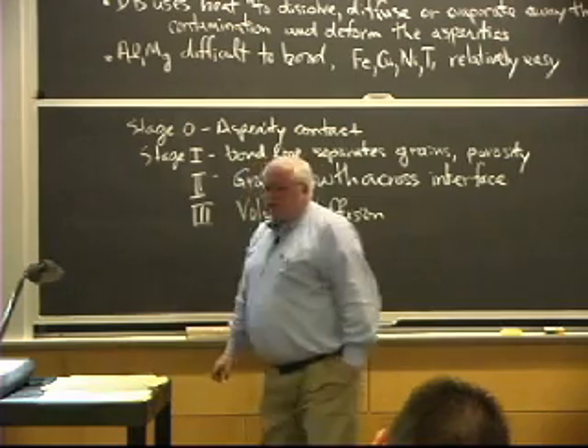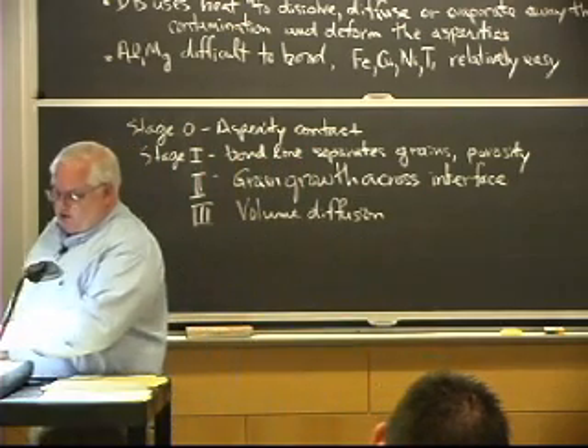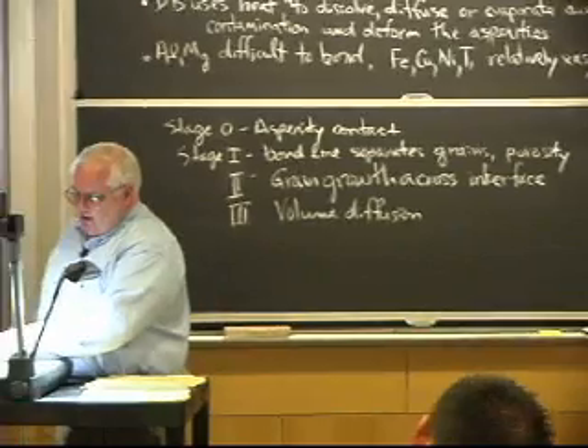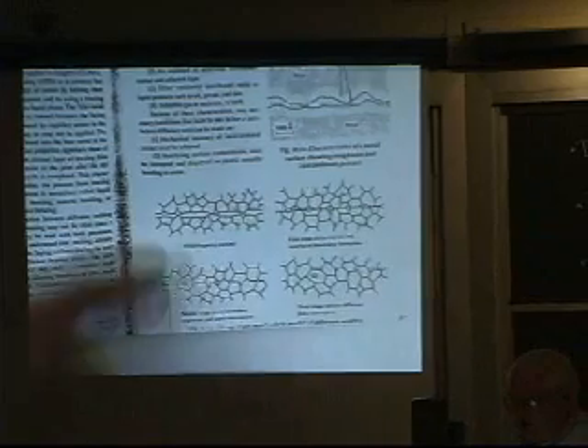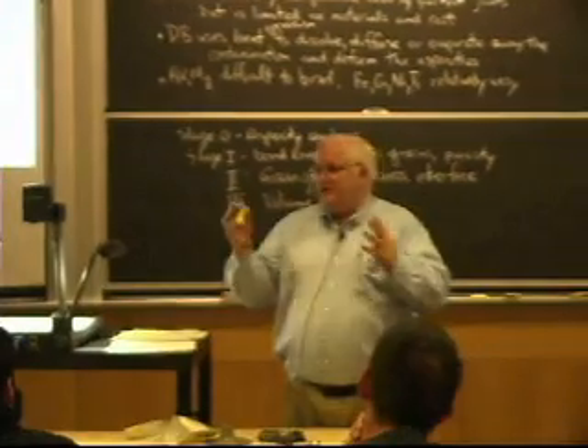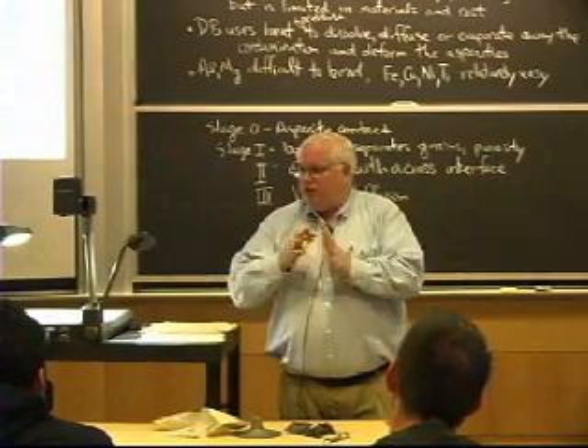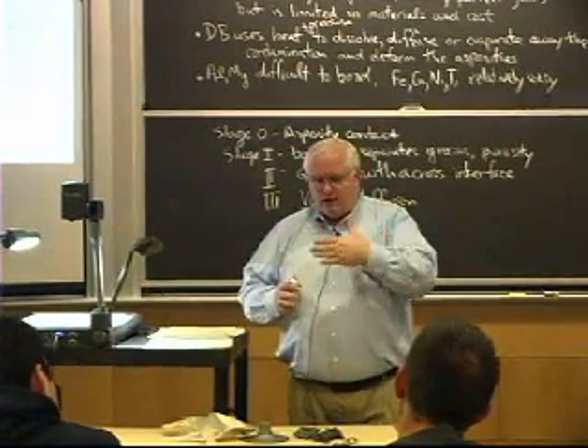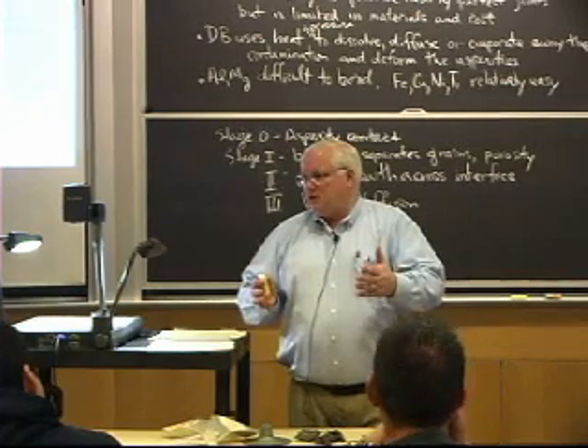And it turns out it's useful to think about this in this way because several things happen. Here's your initial asperity contact. Here you started to diffuse and you now have a perforated grain boundary with separate grains on either side. Here you're starting to get grain growth and you're starting to trap some of the porosity inside a grain. That's a problem. If you know anything about diffusion, bulk diffusion to get rid of porosity takes forever. Now if I have the porosity still contained at a grain boundary, then the pores, the vacancies in the crystal can annihilate themselves just by rearrangement of the grain boundary, and you only have to move a couple of lattice distances to eliminate porosity. Okay?